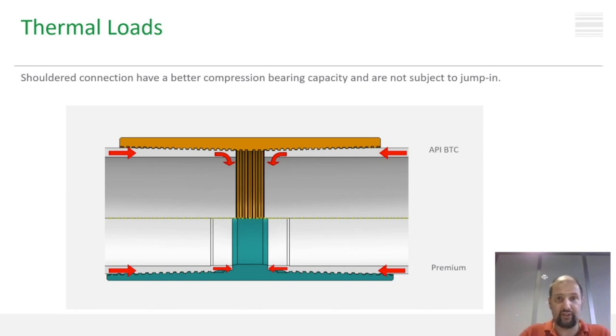For a buttress connection, only the thread is bearing compression load, by loading the stabbing flank of the thread. Excessive compression may lead to a jump-in, that is commonly detected by an inner diameter restriction. A jump-in is when the thread of the pin slides on the thread of the box. As a consequence, the pin moves inwards, causing a restriction of the inner diameter, measured with a caliper or a similar tool, corresponding to the depth of the connection.